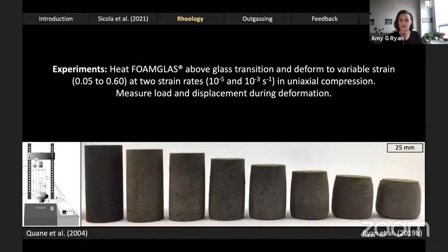So I conducted a series of high temperature deformation experiments using this uniaxial compression rig shown in the bottom left. I cored a bunch of foam glass samples, and I would heat them above the glass transition, which is why their color changes here, and then deformed them to variable axial strain from 0.05 to 0.6 at 2 different strain rates. And I measured load and displacement throughout deformation.